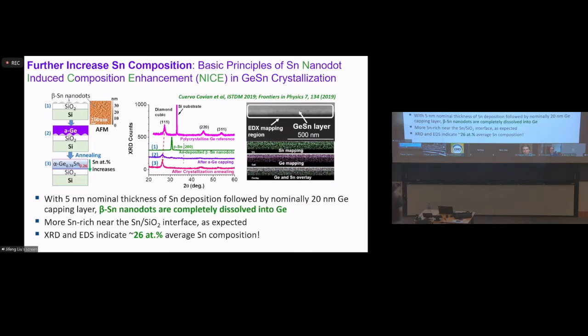And as we put down this amorphous germanium layer, this deposition is slightly above room temperature, maybe like 30 degrees or so, during the thermal evaporation. But essentially, after this deposition, amazingly, this beta-tin peak is already gone. Instead, you see a broad peak over here that's shifted from the pure polycrystalline germanium peak to the left. That means basically it's incorporating tin, so the lattice constant is getting bigger. You can see it's mostly amorphous because the peak is broad.